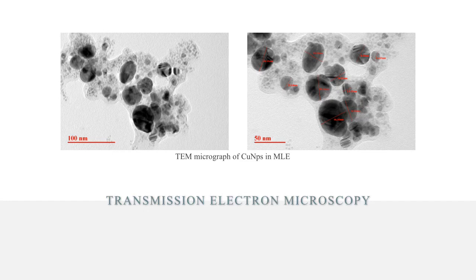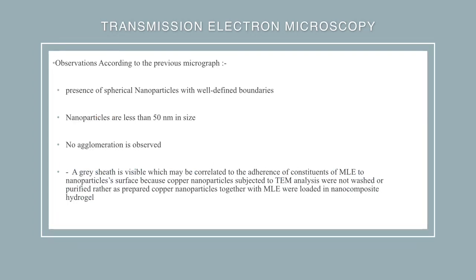According to this transmission electron microscopy micrograph of copper nanoparticles in Moringa oleifera leaf extract, we have some points to be observed. Our observations are the presence of spherical nanoparticles with well-defined boundaries, and that the nanoparticles are less than 50 nanometers in size. There was no agglomeration observed. Also, a gray sheet is visible, which may be correlated to the adherence of constituents of Moringa oleifera leaf extract to the nanoparticles' surface. Because the copper nanoparticles subjected to the TEM analysis were not washed or purified, rather as-prepared copper nanoparticles together with Moringa oleifera leaf extract were loaded in the nanocomposite hydrogel.